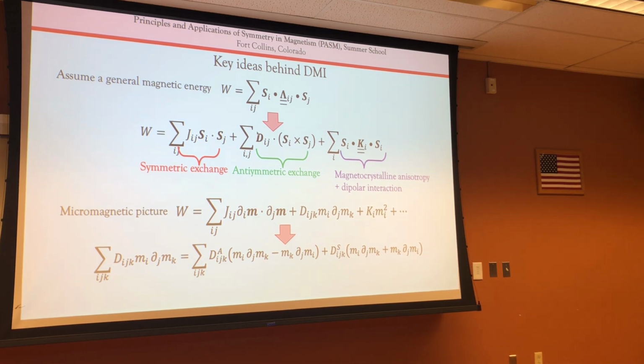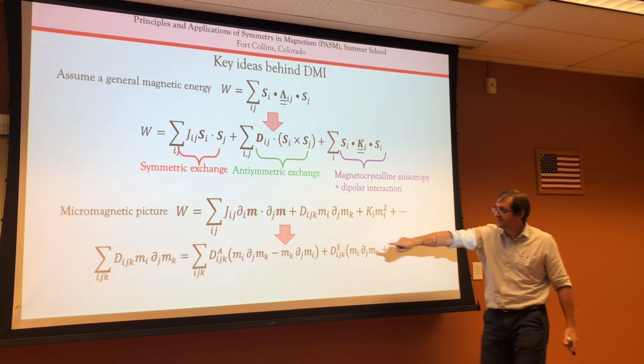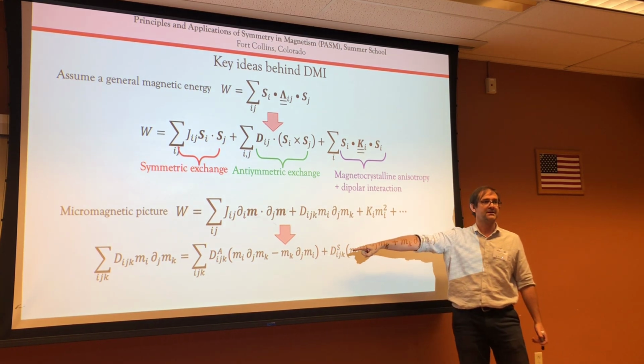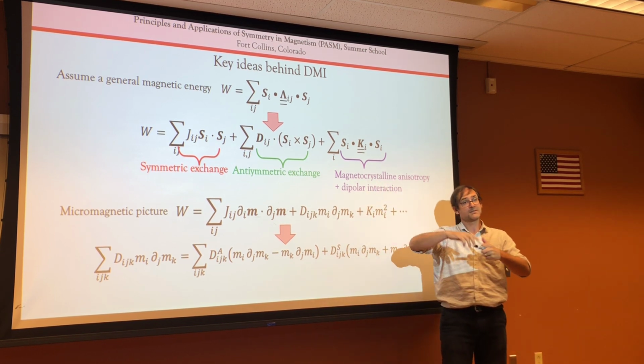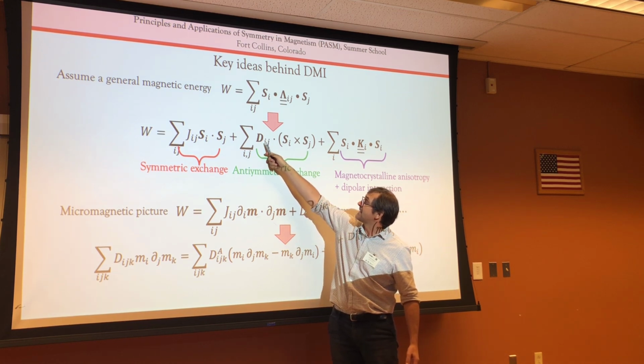Of course, this term here with the Lifshitz invariant is valid for smooth gradients. It's a gradient expansion, so it means that the gradient must be smooth, must be very small, in principle. So if you have any nanoskyrmion or any very strong canting of the magnetization, this one is not valid. You have to go way beyond the linear approximation. But on the other hand, this one is ij, so basically it's between site i and site j.